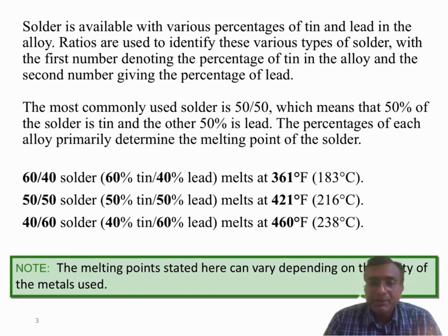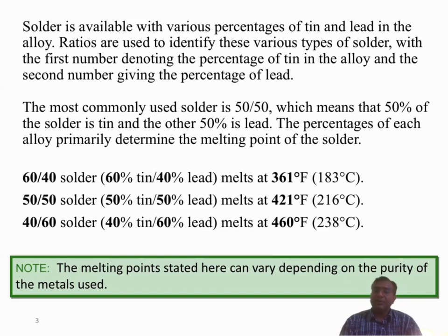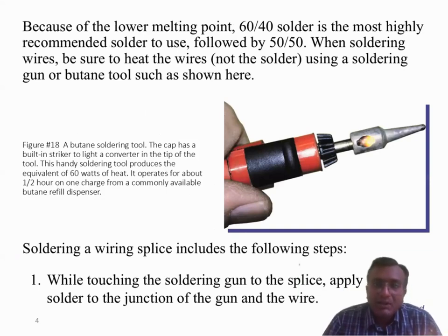For example, a 60-40 solder, which consists of 60% tin and 40% lead, melts at 183 degrees centigrade. 50-50 solder melts at 216 degrees centigrade, and 40-60 solder melts at around 238 degrees centigrade. The melting points stated above can also vary depending upon the purity of the metals used in the solder. Now, in case of 60-40 solder, the melting point is low, and that is why it is commonly used for room temperature applications.